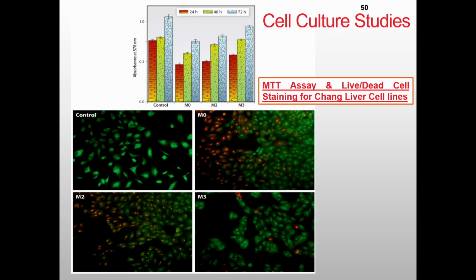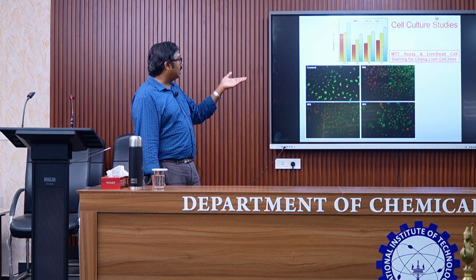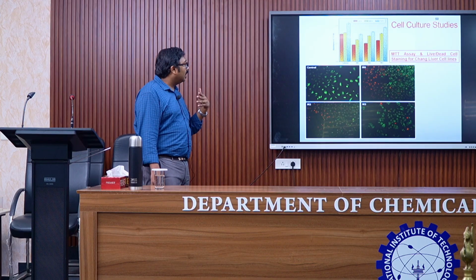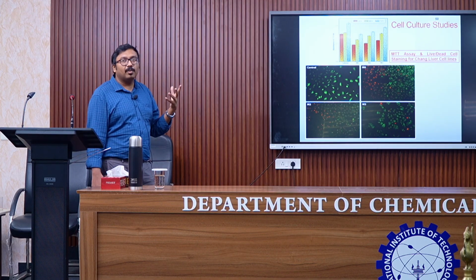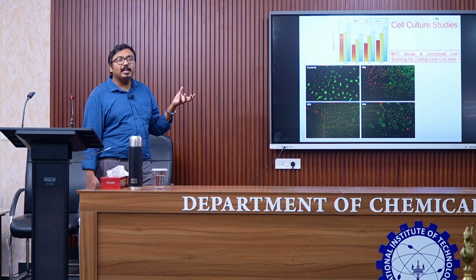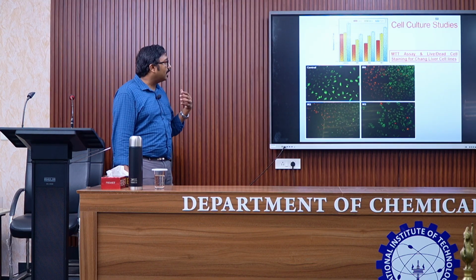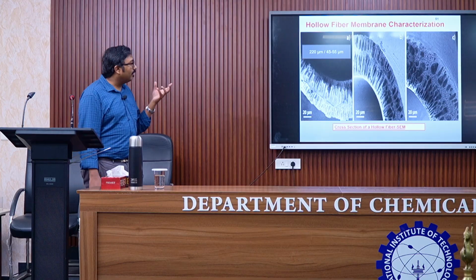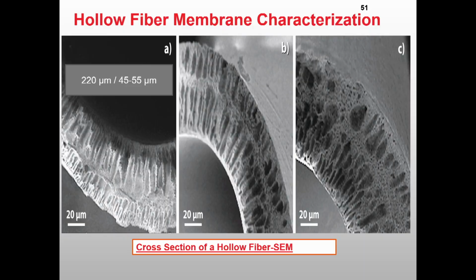Again, we did live cell, dead cell culturing. Like I said, we do not actually want cells to adhere on the membrane surface, but we saw that there was small adhesion on the membrane, but those cells did not die. This is just for the sake of evaluating whether a cell would die when it comes in contact with our membrane surface. And these are the hollow fiber membranes, the cross section of a single fiber. This single fiber has a diameter of 220 micrometers and a wall thickness of 45 to 55 micrometers.